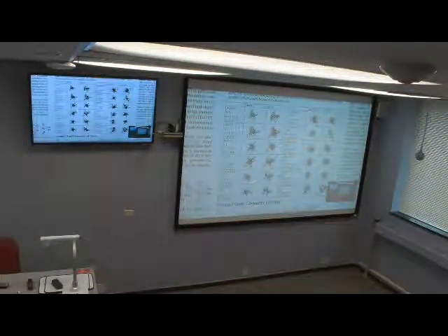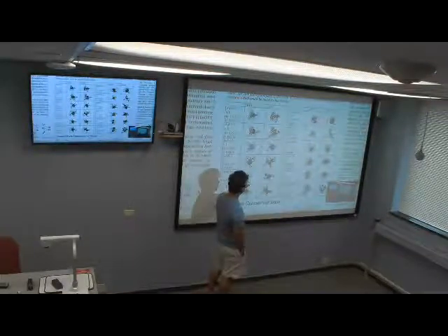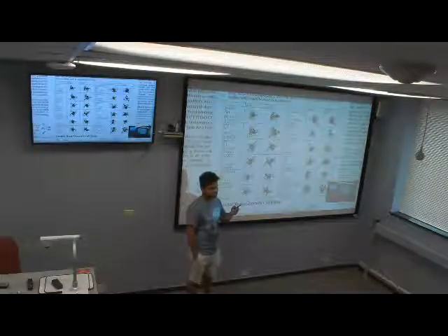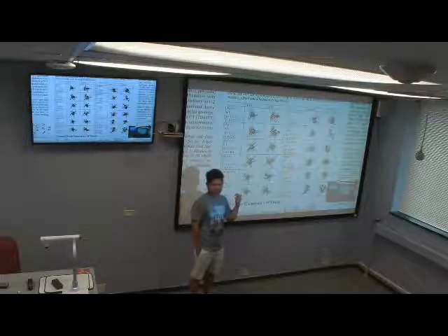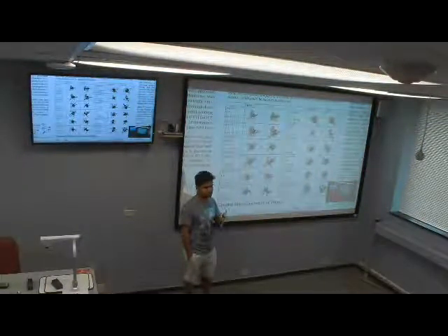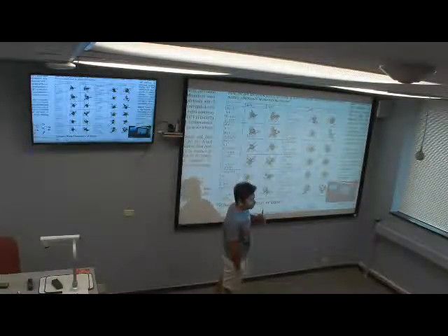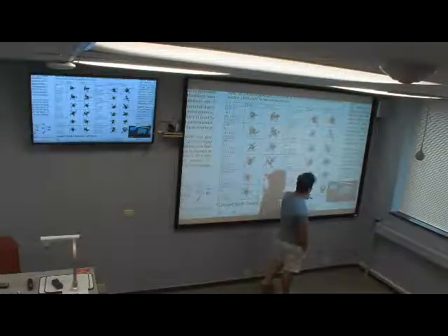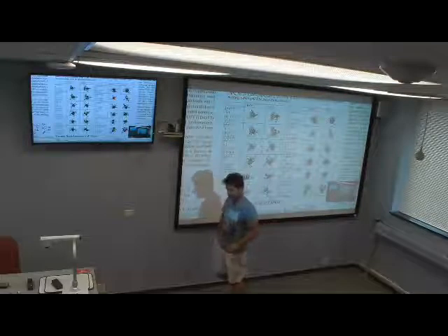And this is showing NTOs, so as I said, it's showing the transition nature. This one is mostly d to d transitions, silver-silver transitions. But I had one question at one time, the contribution of the s to d transition and d to d transition. I don't have a specific answer, but I'm going to include that in my new poster. I calculated this one. And the main peak, the highest intensity peak, the main contribution is coming from the silver to ligand transition.